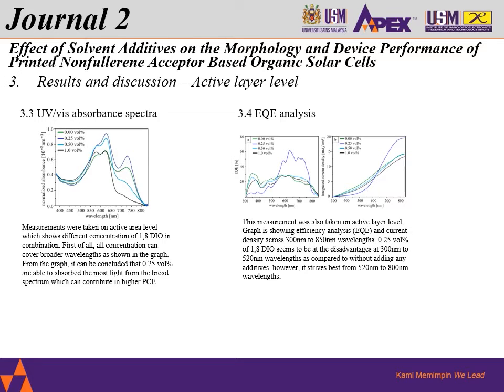Then let's take a look at the EQE analysis. Similarly, let's look at the 0.25% volume concentration, since we know this gives the highest efficiency reported in this journal. From 300 to around 520 nanometer wavelength, it has surprisingly low EQE. But when it goes beyond 520 nanometers to around 780, there's a peak, a very distinctive EQE as opposed to other concentrations. So it means that 0.25% DIO is more favorable with this 520 to 780 wavelength.